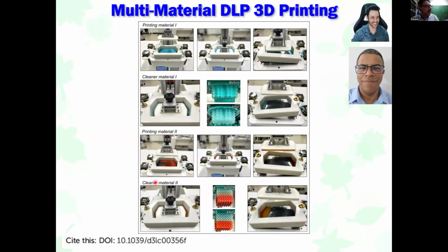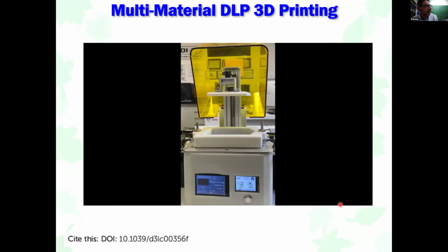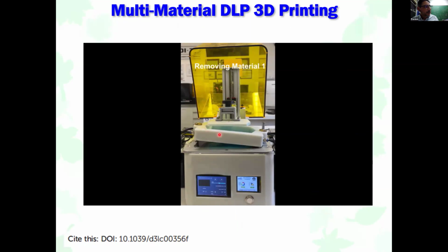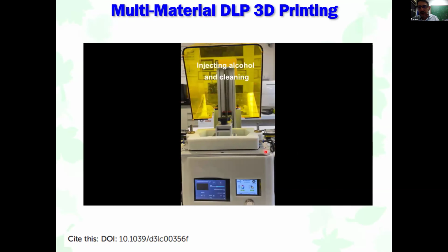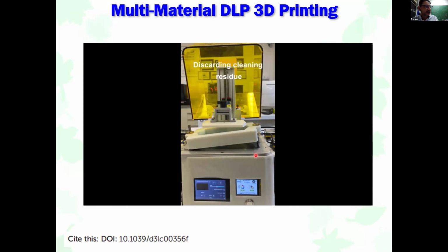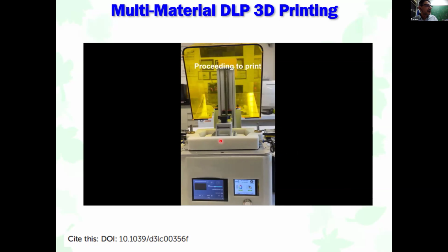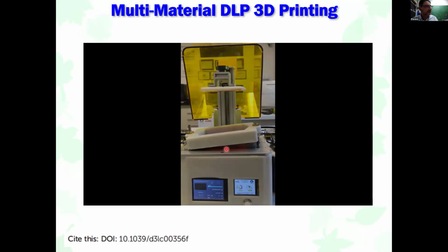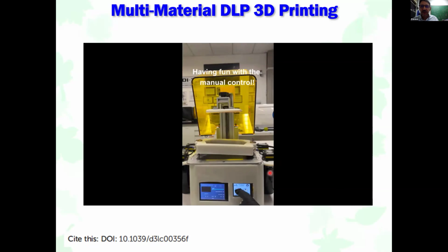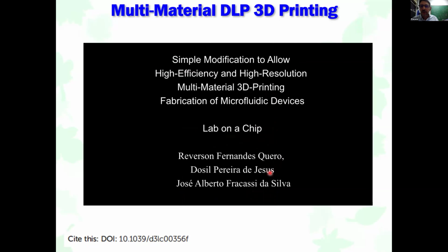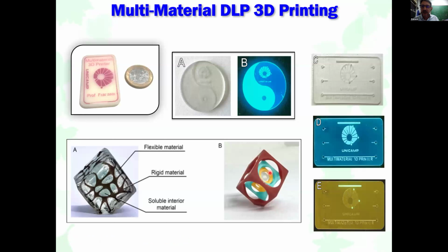So these are some pictures of the process, but I have a video here. They start printing, with the material already inside. Then you remove the first material and return it to the reservoir of the material. You clean the device to remove the residues of the material. Inject the second resin. It is injecting. You proceed with the printing for the next layers you want. In this case, the process was finished. But you can also have any number of layers you want if you adjust the number of reservoirs you have on the inlet of the tank.